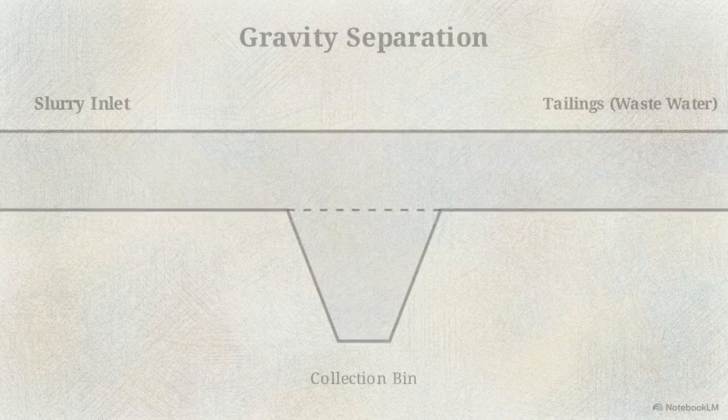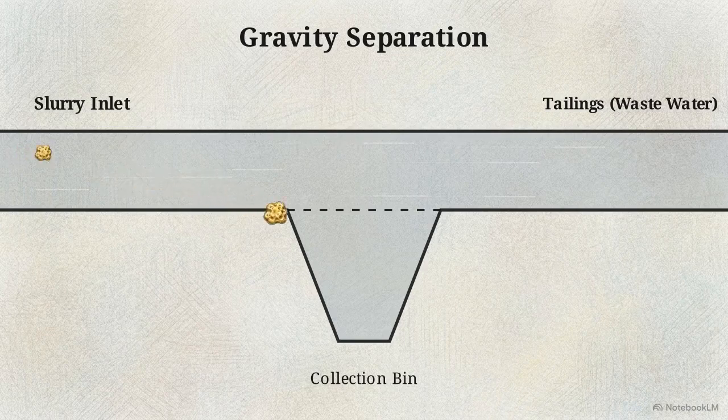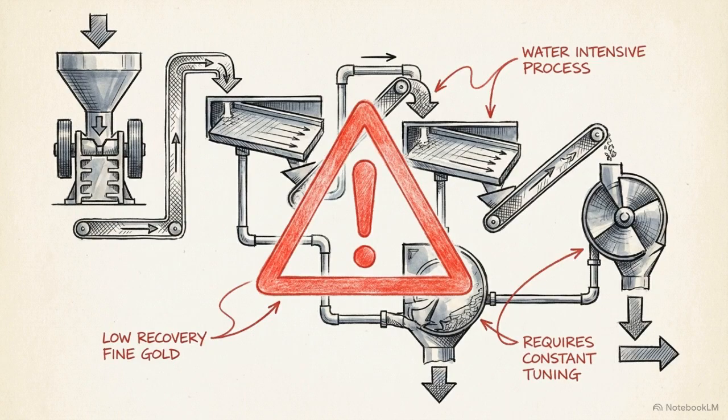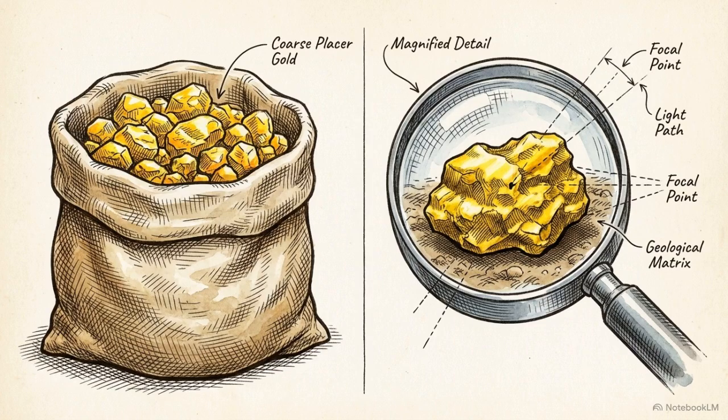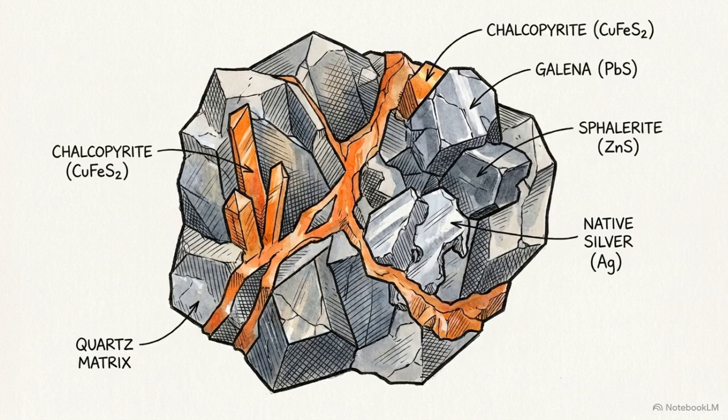This diagram illustrates the physical limitation of a gravity separator. When dealing with complex or fine-grained deposits, the heavy material sinks, but the ultra-fine gold is light enough to slip past the mesh and flow out with the wastewater. If an operator relies solely on a gravity circuit to process a mixed-grade or fine particle deposit, they wash their own yield directly into the tailings pond. While a gravity-only flow sheet creates a profitable low-overhead operation, it must be restricted to deposits where the gold is loose, large, and visible. The math changes when we encounter complex polymetallic ores.